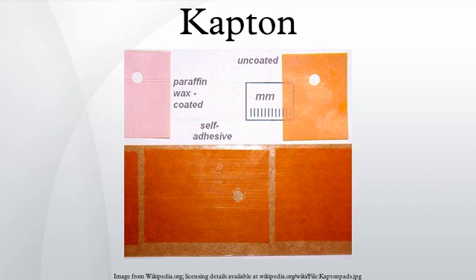However, Kapton insulation ages poorly. An FAA study shows degradation in under 100 hours in a hot, humid environment. It was found to have very poor resistance to mechanical wear, mainly abrasion within cable harnesses due to aircraft movement. Many aircraft models have had to undergo extensive rewiring modifications, sometimes completely replacing all the Kapton-insulated wiring, because of short circuits caused by the faulty insulation.